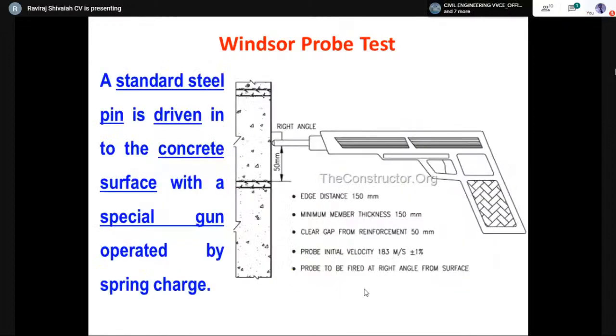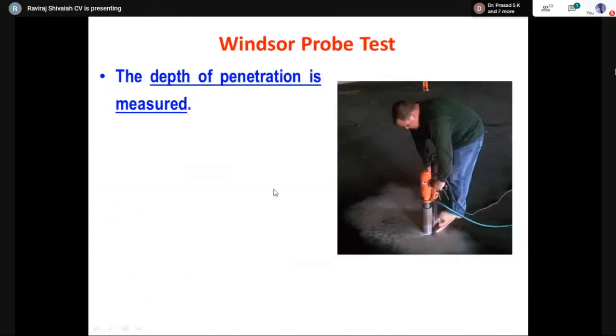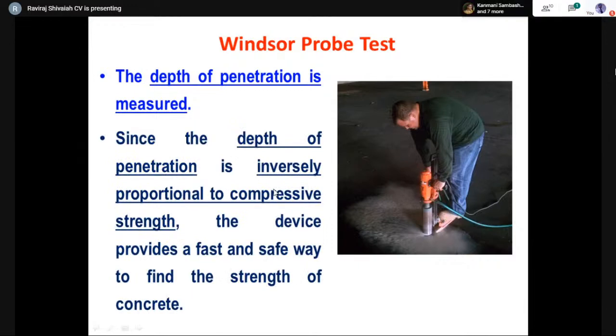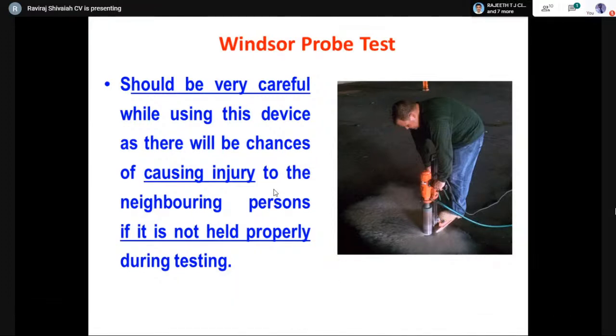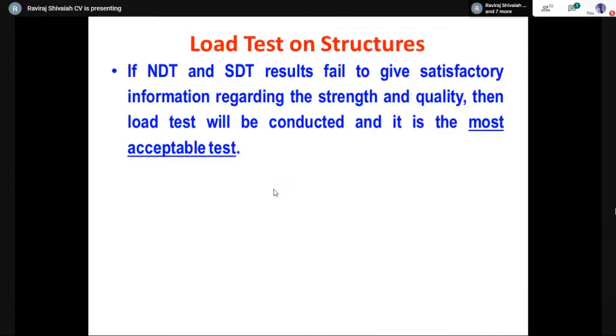Now let me go to the next one, the Windsor probe test. This particular test is quite simple. We take an apparatus similar to a gun, keep it on the surface, and fire a metal bullet over there. If we get more damage, it represents that the strength of the concrete is less. It's a very simple test. The only thing is we have to be careful to do the test properly. So this is called the Windsor probe test. You keep the gun in contact with the surface and then fire it appropriately.